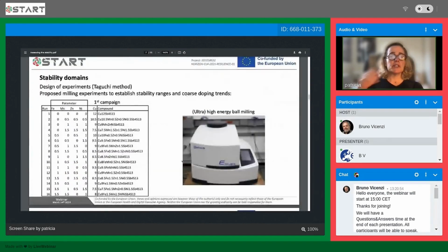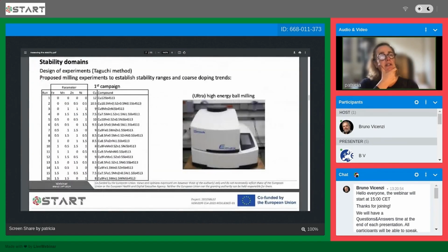One of the first experiments we did, we decided to use a design of experiments. We decided to use the Taguchi method, but we were a bit too wild, so we went to very high variations in composition, which in the end revealed to be not the good choice. At the lab, in addition to what Serena is doing at an industrial scale, we also use this very high energy ball milling. This is a machine that allows you to really make sure you put all the elements into a solid solution.